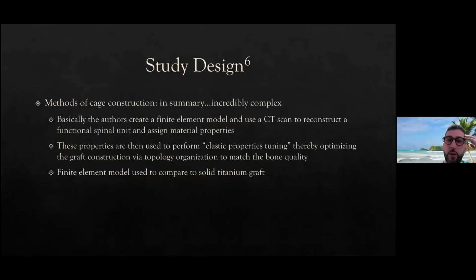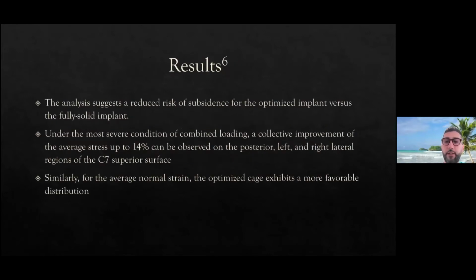And so, it's a relatively complex study, but they use finite element analysis, which is basically a simulation. And so they take a CT scan, they reconstruct a functional spinal unit, they assign it material properties, and they use that to basically tune a titanium graft to optimize its graft construction and topology to match bone quality. And then they do this finite element analysis to compare it to this all titanium graft.